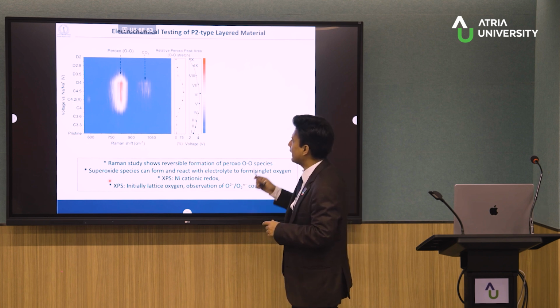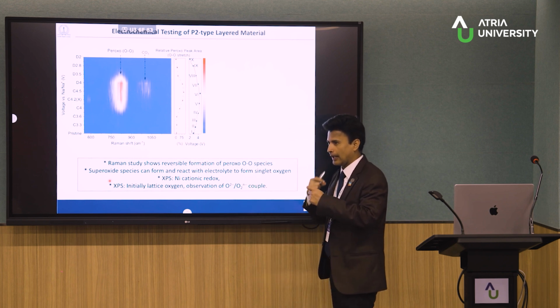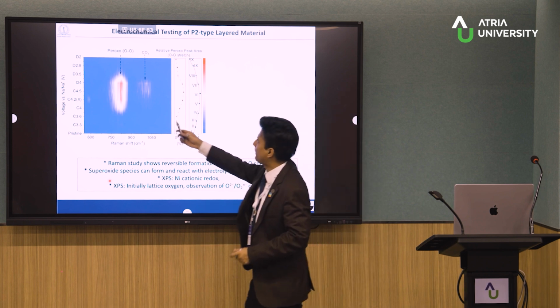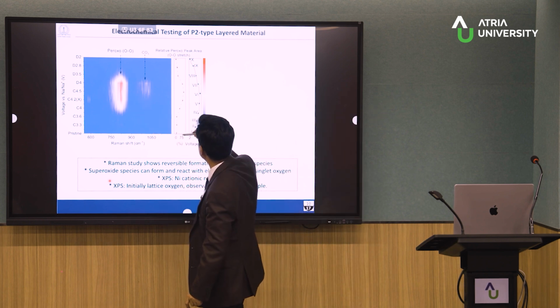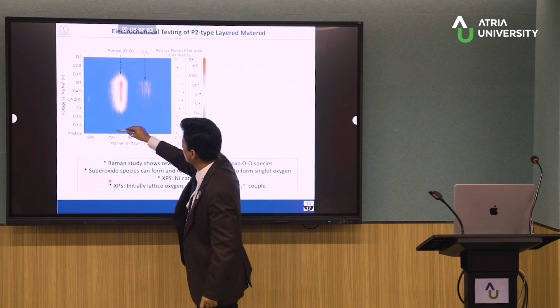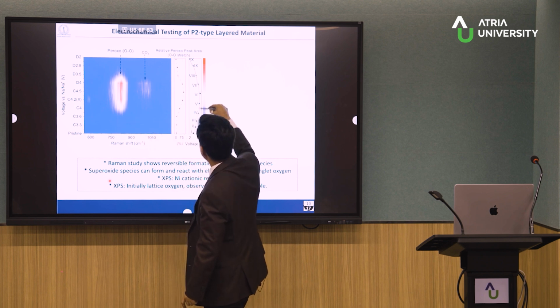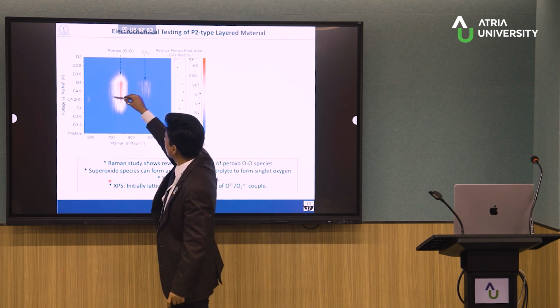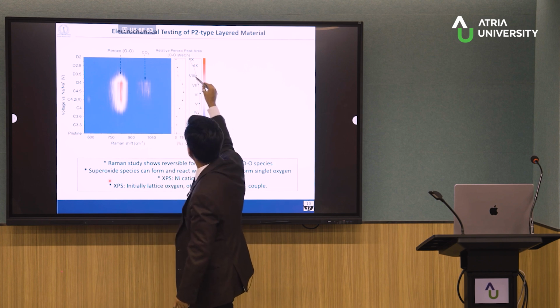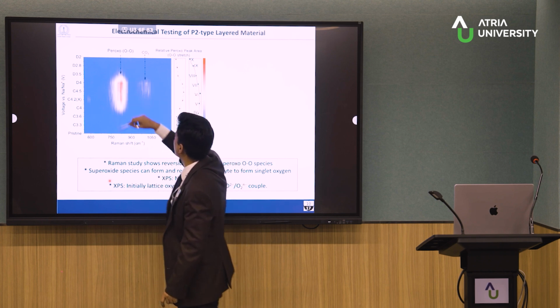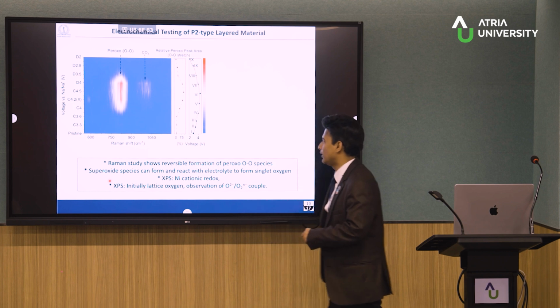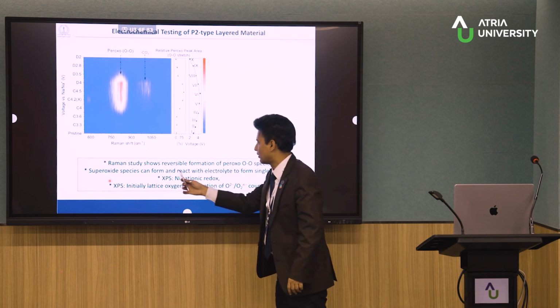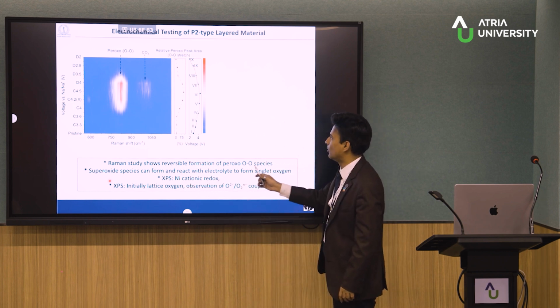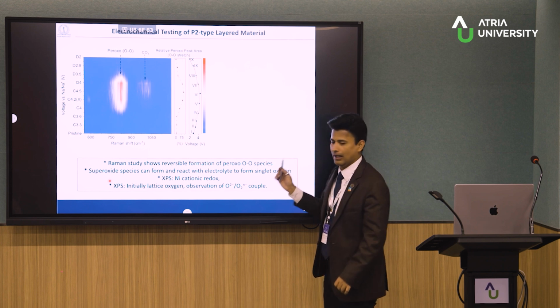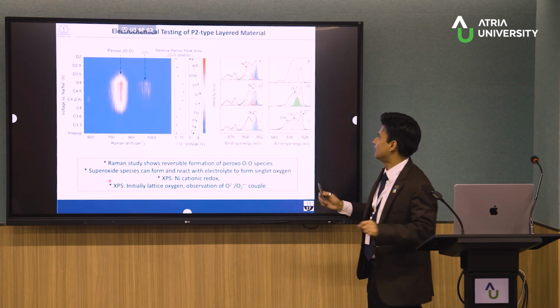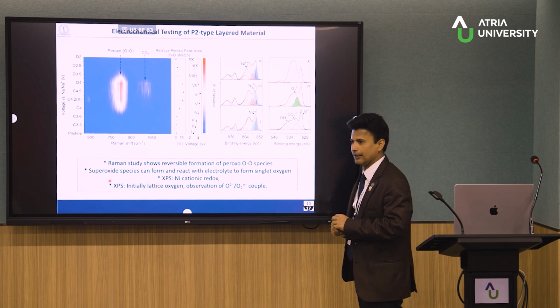In Raman, actually when we do some anionic redox, when there is a peroxo bond formation at high voltage, this is the low voltage, peroxo is not there, at high voltage where the anionic redox is happening, we get some peroxo bond, again upon discharging, again they disappear, again it comes back to normal. So with Raman study we saw some reversible formation of peroxo O-O species which is easily captured, and also we did some XPS analysis in IISc.